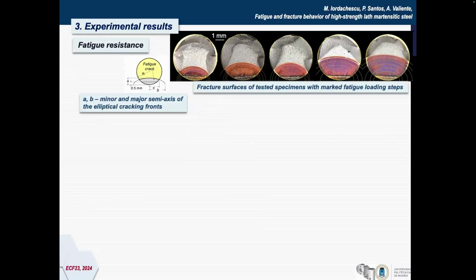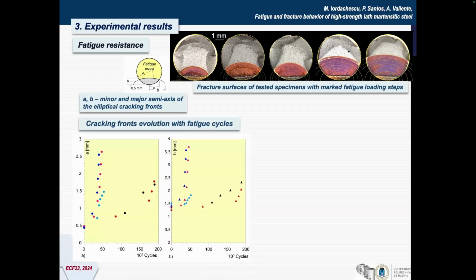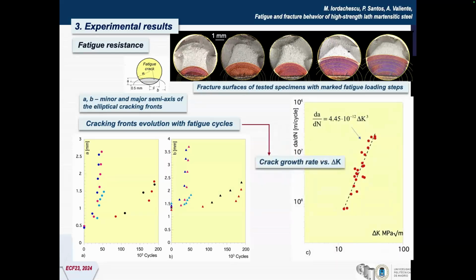to the fatigue resistance, here you have some images that present the fracture surfaces of the tested specimens with the marked fatigue loading steps by heat tinting, because the tests were interrupted after some loading cycles, and the specimens were subjected to heat tinting. And at the end, we get the minor and the major semi-axis of the elliptical crack front. Thus, we plot the crack front evolution with the fatigue cycles applied, and also the crack growth rate versus delta K.